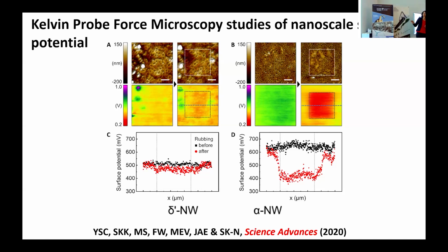The top images are all topography, and the bottom images are all looking at the surface potential at the top of these nylon nanowires. In the first image, we just measure what the surface potential is. In the second image, we zoom into a smaller subsection of the image, and we use the AFM tip itself as the rubbing element, right? So we use that to transfer some charge, and then you can zoom out and see how much charge you managed to transfer.